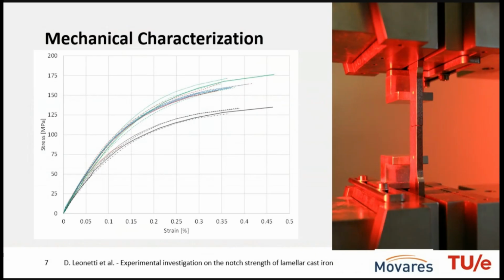Now, what you can observe are a few peculiar aspects: the Young's modulus is way lower than steel, half the value, 100 gigapascal, and you may not be able to define a yield stress, because sometimes the ultimate tensile stress occurs below the 0.2% residual strain. So, in fact, usually for this kind of material, in standards that are used to characterize and categorize the material, it is referred to the 0.1% residual strain.